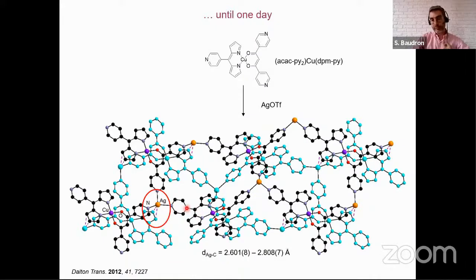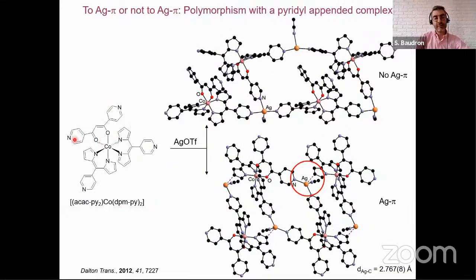So even though the coordination involves pyridyl groups, in this case, we do still observe a silver-pi interaction, although with longer silver-to-carbon distance. So even with those types of ligands, we can observe this mode of assembly. And it seems that there is a fine balance between the presence and the absence of this interaction, because indeed, when we are using this heteroleptic cobalt complex and we assemble it with silver cations, we observe polymorphism or pseudopolymorphism in this case, where we have different types of crystals within the same batch. In some crystals, we do not observe silver-pi interaction, only coordination of the acetonitrile molecule with the free pyridyl units. And in other cases, an eta-1 mode of assembly of a silver to the carbon-carbon double bond.